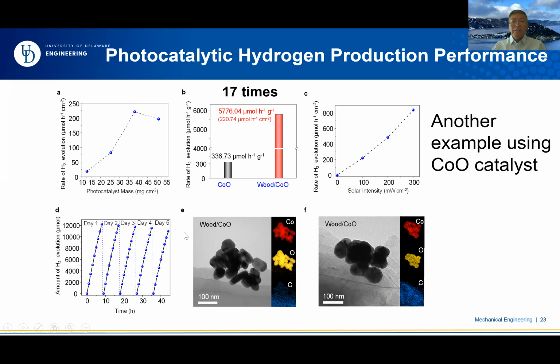And also we test the lifetime, again to see how stable the catalysts attached on the wood structure. And here we test for continuous 5 days, 8 hours per day. And you can see the retention of hydrogen production is up to 90%. For all the demonstrated systems reported in the literature, it's hard to achieve such a good stability.